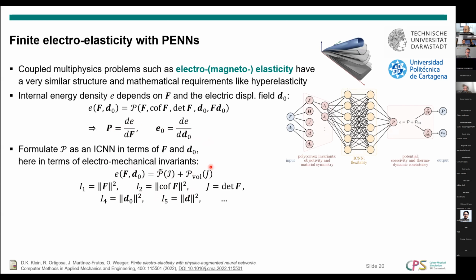And then this term is just this additional analytical term that ensures the growth conditions. So our model architecture, you see it up here, basically. We have the deformation gradient, we have the electric displacement field vector. With these, we generate also the cofactor and these combined variables, and then from that we compute the invariants, and then the invariants are the inputs for the input convex neural network.